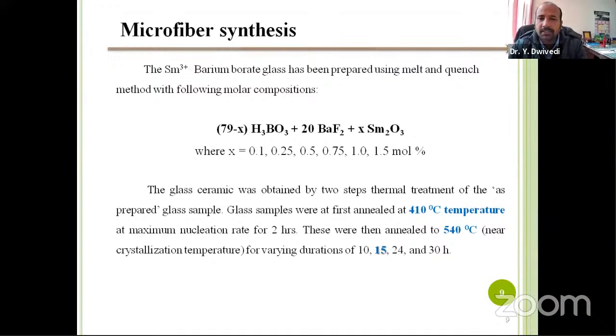That transmitting glass we kept for heating purpose, two-step heating. First at 410 degrees Celsius, already optimized much before, near the nucleation temperature, and then heat it at 540 degrees Celsius, which is near the crystallization temperature, though the crystallization temperature is around 600 degrees Celsius approximately.